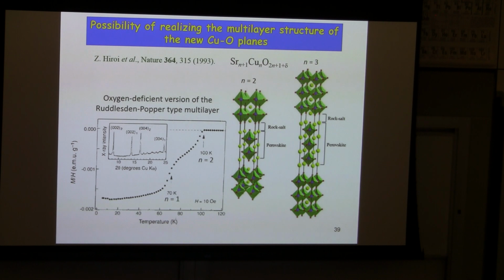Okay, this is not so unrealistic, I should say. Already in earlier days, there was some possibility for the multilayer structure for the strontium counterpart. Actually, these authors proposed some multilayer structure, but at that time, no one knew that this cuprate has an oxygen deficient oxygen plane, but they proposed this multilayer structure. This is the so-called Ruddlesden-Popper type multilayer, which has quite equivalent inner plane and outer plane situations.